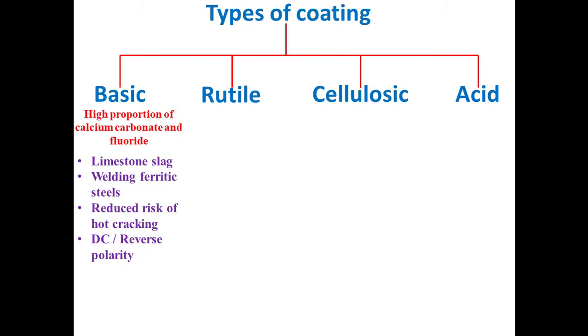which is favorable for the welding of ferritic steels, and this desulfurizing effect will reduce the risk of hot cracking of the deposited weld. And it's to note that when we use a basic coated electrode in welding, it's recommended that we use direct current with reverse polarity, and it's also recommended to carry out stoving of these basic coated electrodes at 350 degrees Celsius for 2 hours.